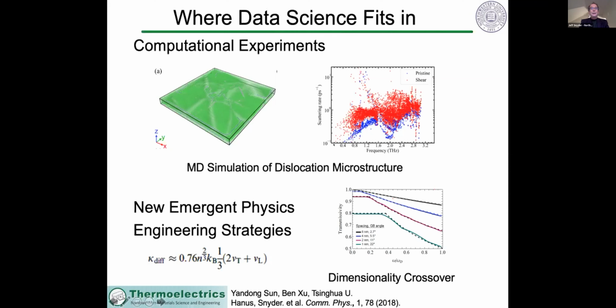And I think computational experiments might be the way to do that because there's so much more information involved in such an experiment. So here's, for example, an MD simulation of a structure with a dislocation microstructure, which obviously is very complicated. And then thinking about the scattering rate of each individual phonon mode is going to be quite complicated. So to me, data science can help do those calculations as well as interpret them.